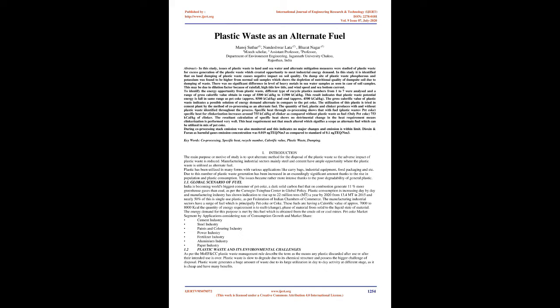The utilization of this plastic was tried in a cement plant by the method of co-processing as an alternate fuel. The quantity of fuel, plastic, and clinker produced with and without plastic waste was identified throughout the process. Specific heat through co-processing shows that with plastic waste and pet coke as fuel, the specific heat for clinkerization is around 755 kcal/kg of clinker, as compared to 753 kcal/kg of clinker without plastic waste, with only pet coke.